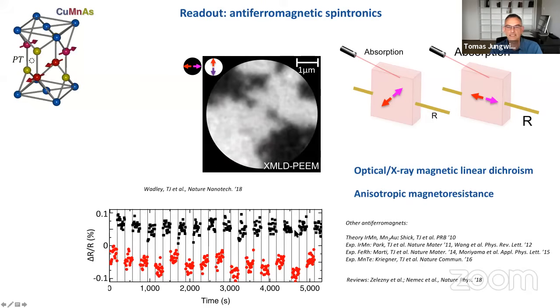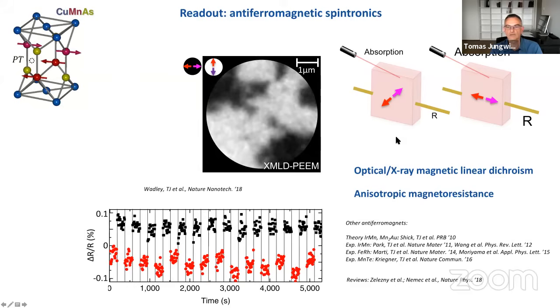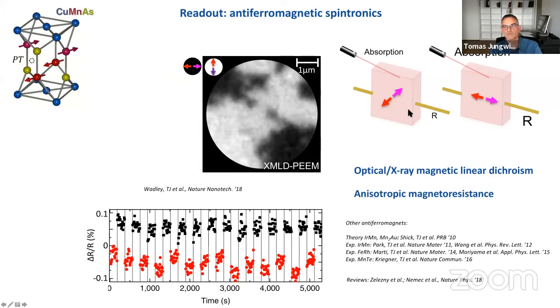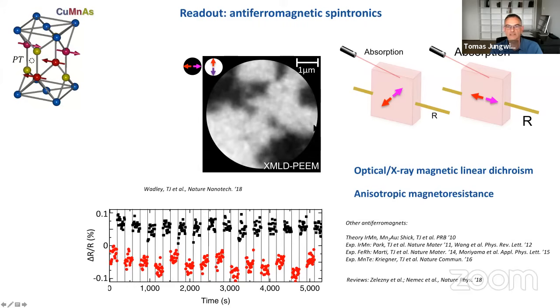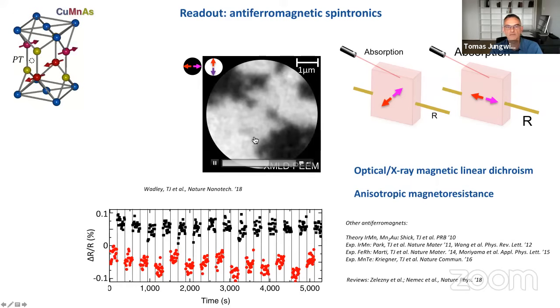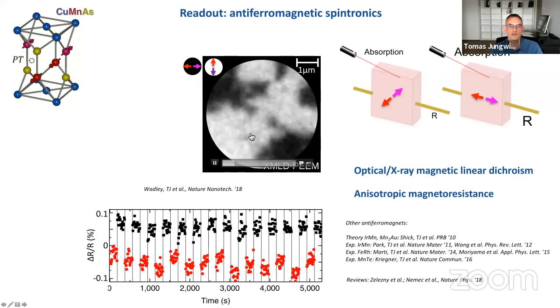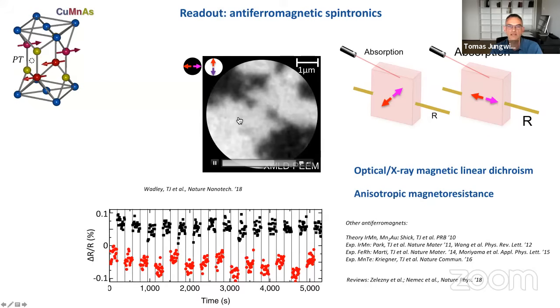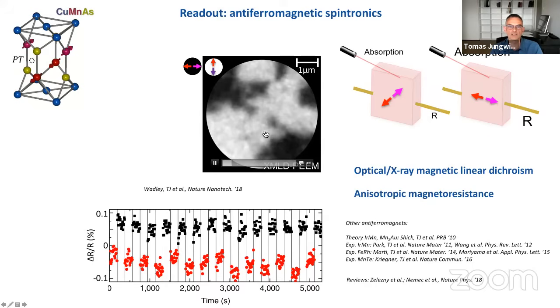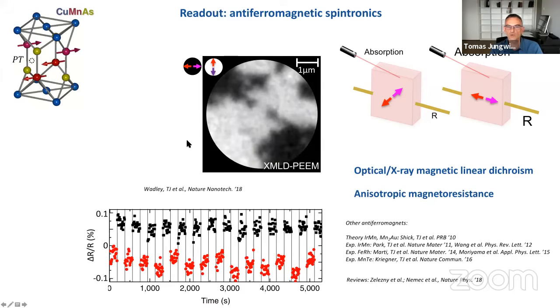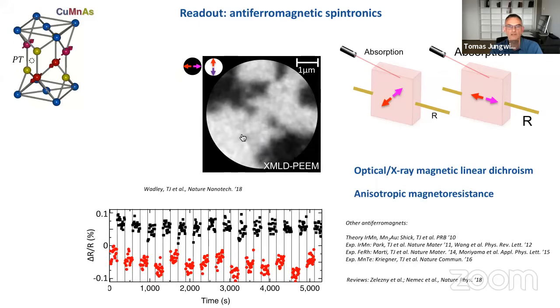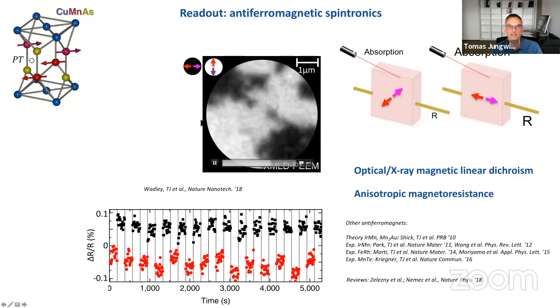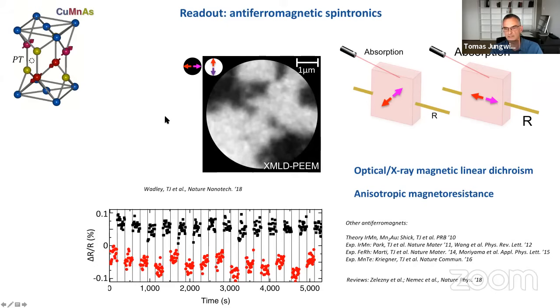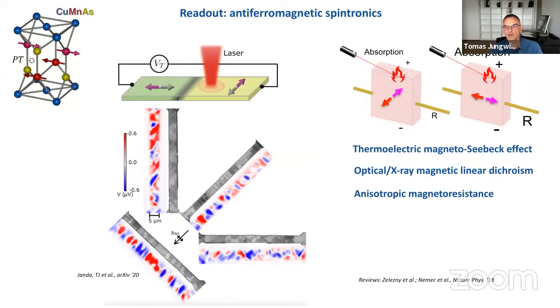So besides the electrical signal, which probes the average change over the entire electronic device, in this microscopy, we can zoom in and look at individual domains. So these are micron-sized domains. And what you see in this movie is switching between the two orthogonal directions of this several micron size domain in copper manganese arsenide.